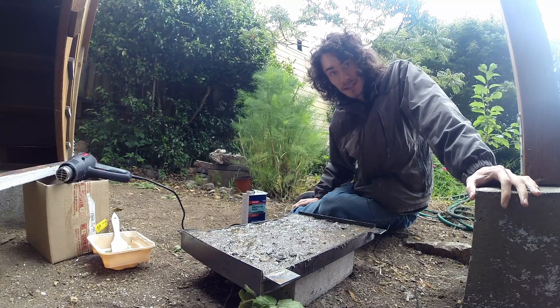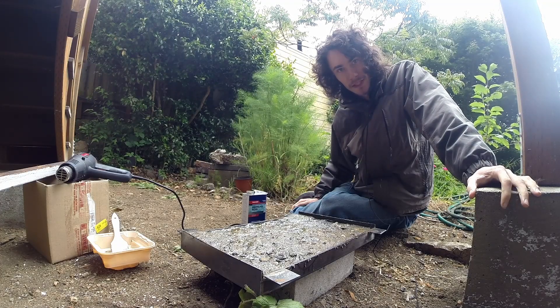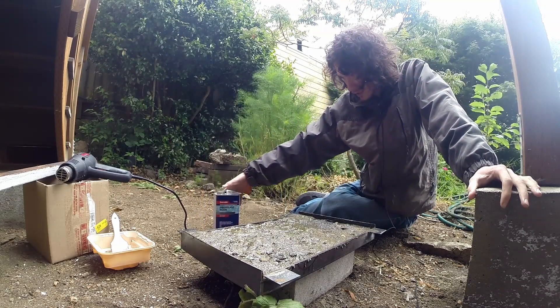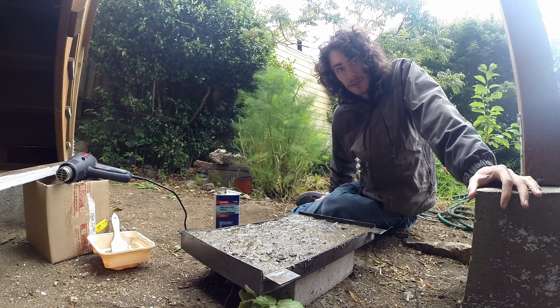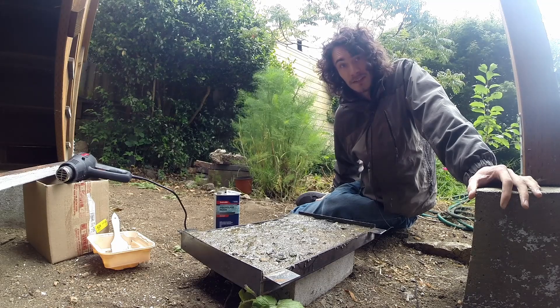It's the next day — today is actually July 4th, so happy Independence Day to everybody in the USA. In short, what I did over yesterday was I felt like the epoxy I was using just wasn't enough to provide a good strong bond. So I ran to the local Lowe's and picked up some Bondo fiberglass resin. It works pretty good except I forgot that this stuff is crazy moisture sensitive, and it turns out the sand in the bag comes wet.